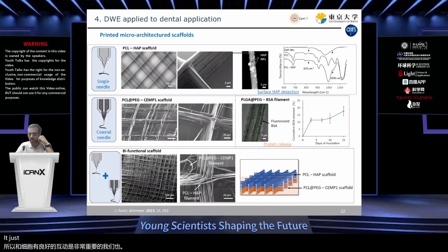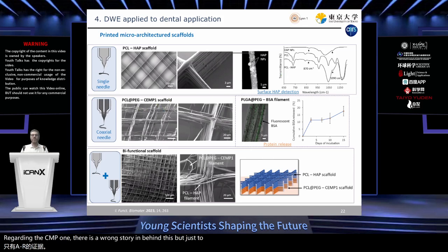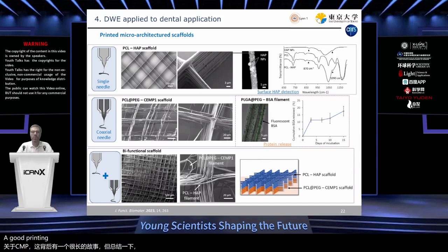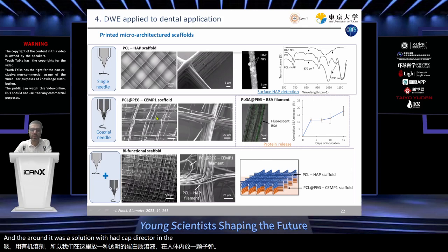just evidenced this with the FTIR. Regarding the CEMP1, there is a long story behind this, but just to summarize, we used a coaxial printing in order to prevent the protein to be in contact with the organic solvent. So we put here aqueous solution of protein with a polyethylene glycol, and around it was a solution with a polycaprolactone in the organic solvent.